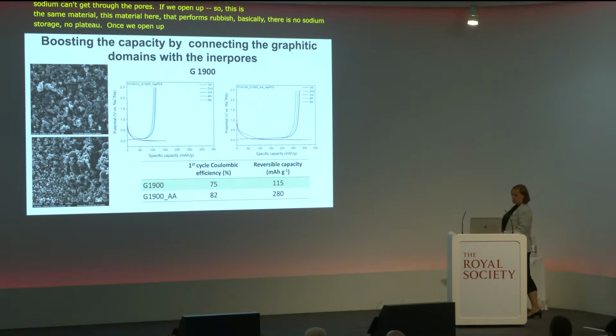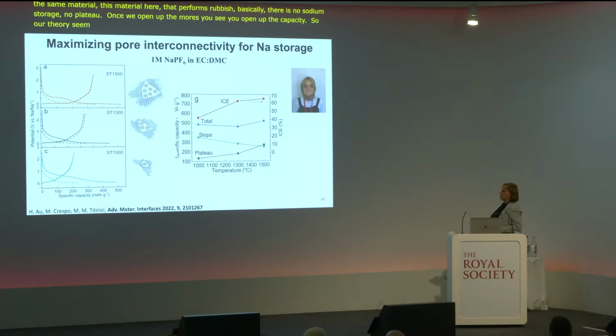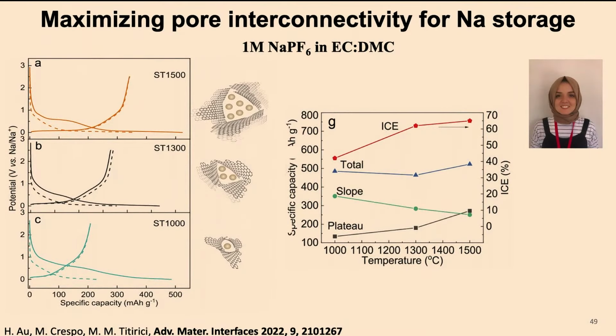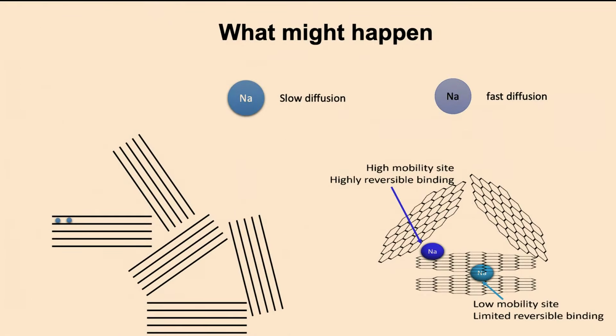So our theory seems to be right, and then my PhD student Hande has been proving this theory further, where she created carbons with the right interlayer spacing between these graphene layers and larger pores, and we could get to impressively high capacities. So what is happening is something like this, I'm a very bad drawer. Sodium goes in, and you need enough interlayer spacing for metallic sodium to go in. This storage is very fast in the sloping region, and you can make it even faster by putting in more oxygen or defects, so sodium can make fast-charging batteries. And once it's in the pores, you can increase the capacity.